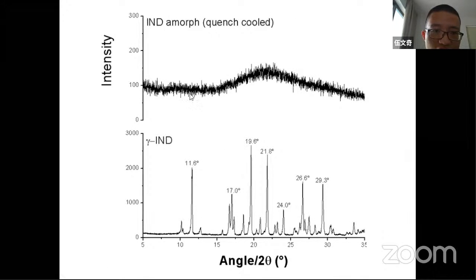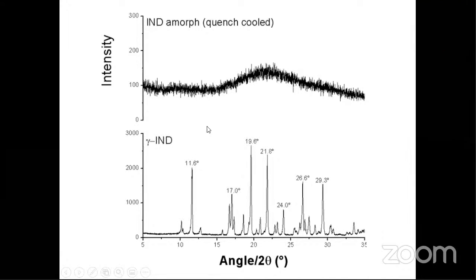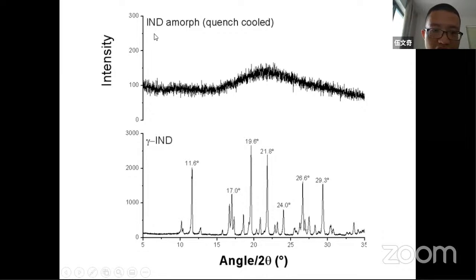For amorphous and crystalline forms, different polymorphs - we can see here with indomethacin, a drug we showed a few slides earlier. When you use the quench-cooled method to prepare amorphous indomethacin, we can see from the XRD results, from 5 degrees to 30 degrees, there are no sharp peaks. This is what we call a standard amorphous halo. And gamma indomethacin is form gamma.